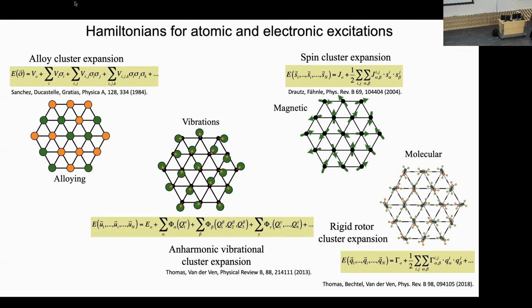And let me just illustrate it with this alloy cluster expansion as one of the examples. So it has a form like this, kind of a linear expansion. The way this works is we want to know how the energy of an alloy depends on the way you decorate this alloy. So you've got this parent crystal structure, in this case a 2D triangular lattice, and you have different ways of arranging orange and green atoms. If you have a green atom, you introduce these occupation variables, which are +1 if the site is green, and -1 if it is orange. And so each site has one of these occupation variables.